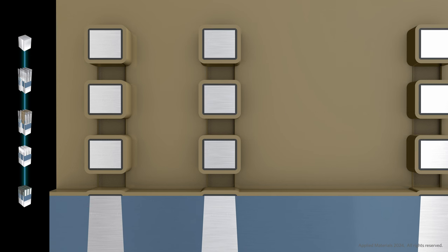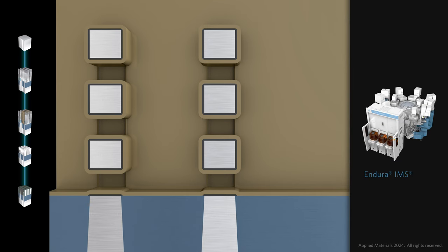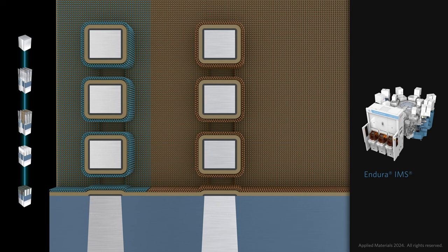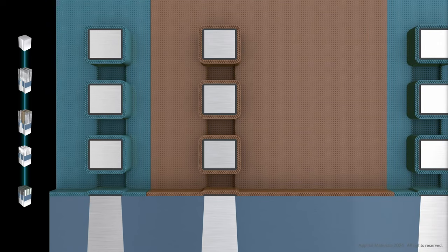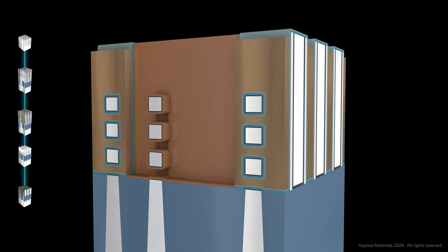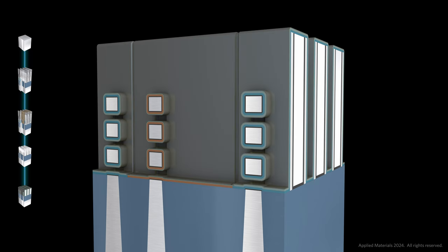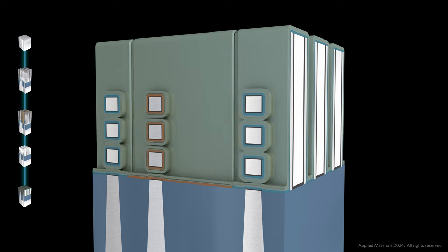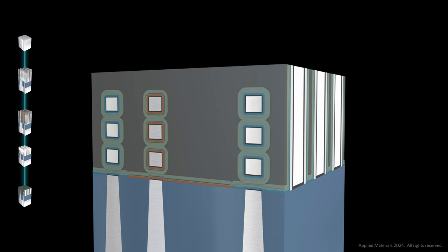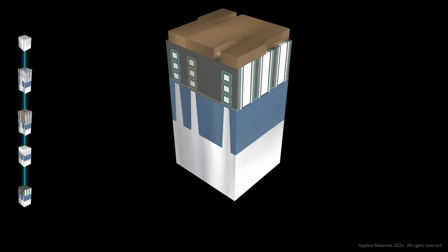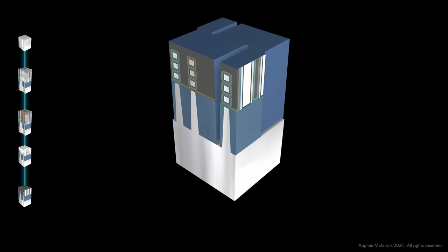To form the multi-layer metal gate in this tiny space, Applied developed an integrated materials solution based on the Endura platform to diffuse a dipole into the dielectric gate layer that surrounds the silicon nanosheets. This step tunes the threshold voltage without adding any volume. Next, the system uses a number of ALD steps to deposit ultra-thin metal gate layers. Multiple layers of metal are atomically deposited in the narrow space. Once the transistor metal gates are tuned, several etch steps are used to partition the larger gate structure. This completes the front end of line fabrication process for the gate-all-around chips.